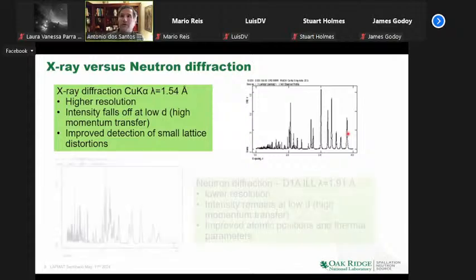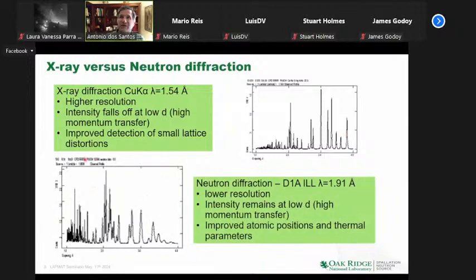If you go to a similar thing, actually this is the same compound with neutrons, you see immediately two things. It has lower resolution, and I'm talking about the peak width, not the image quality, because it's pretty bad actually. But you can see there's a lot more intensity at high Q. And what this tells you is that although you don't see the lattice distortion so well, when you do the Fourier transform, you have so much data to high Q that you have much better atomic positions and thermal parameters. So the local structure of the material is much better known.